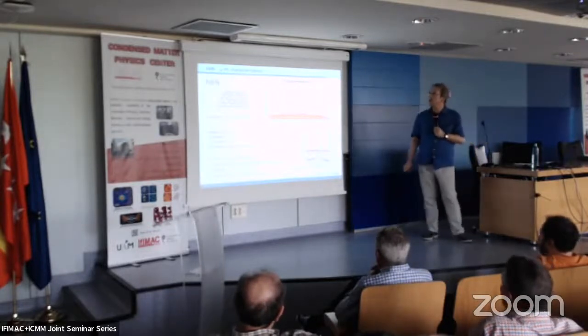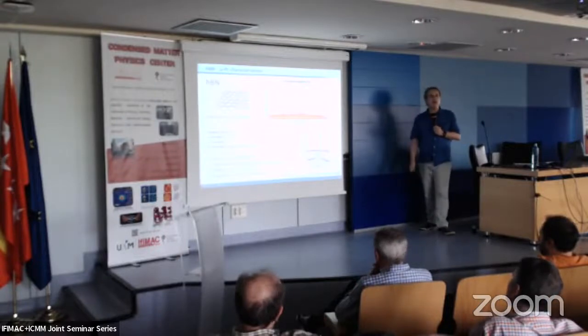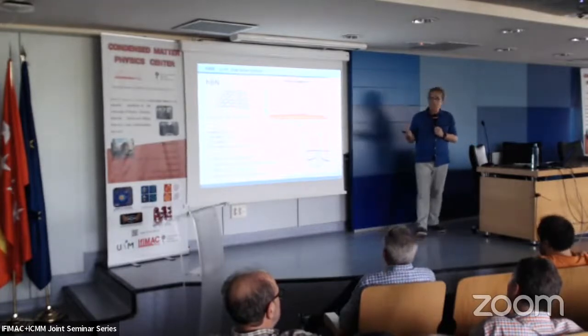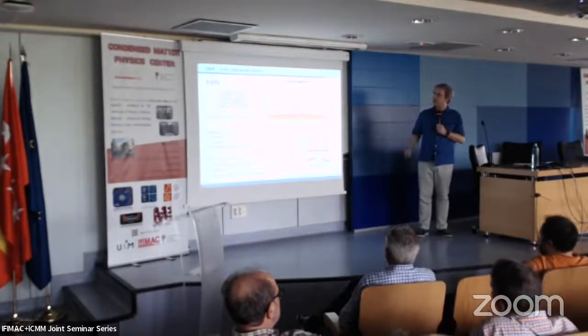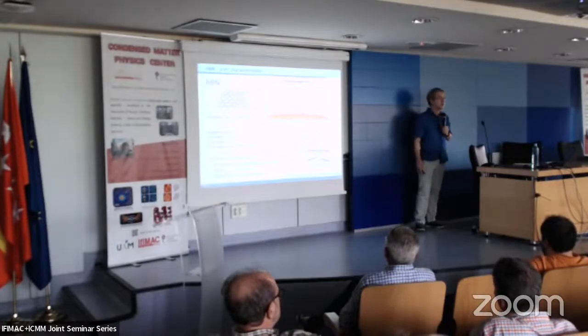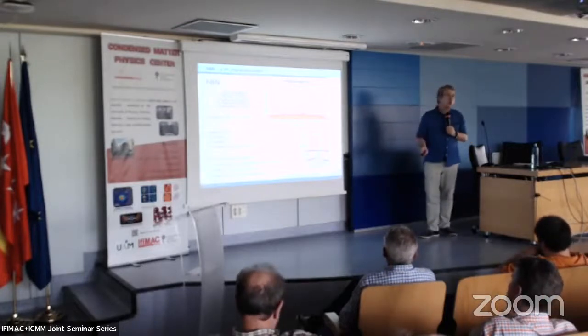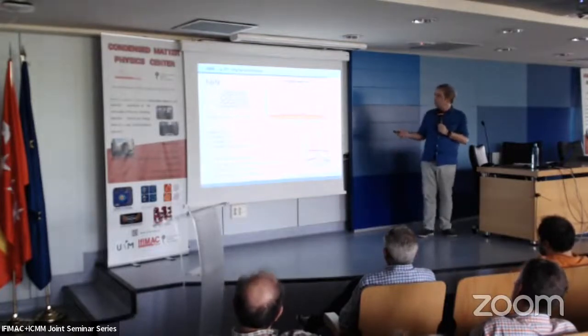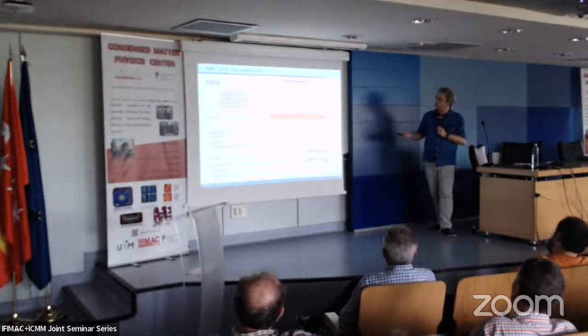The second material I want to talk about is hexagonal boron nitride. Hexagonal boron nitride is one of the materials which was also quite famous in this field of single photon emission, where it's known that defects in the material, like here, can give rise to single photon emission. So it's really localized on the defect. The band gap of boron nitride is about 6 electron volts, which is in the UV. So all those emission lines which you see here in 3 sections of the visible spectrum correspond to energy much lower than the band gap.